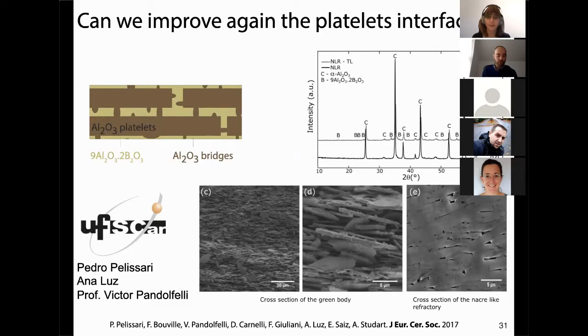And so what we ended up is teaming up with the University of São Carlos in Brazil, because they have a huge experience in ceramic and refractories, and they said, okay, if you're doing alumina, just use this compound, this aluminum borate. It's the best glassy crystalline phase we know for alumina composites and alumina refractories. So you should just try to do that.